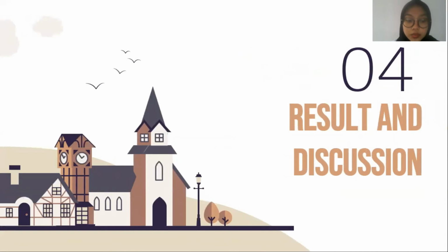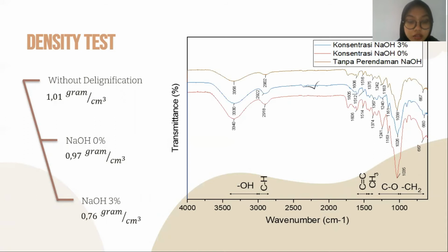And then the next chapter is about the result and discussion of this research. This is the result of the density test. Fiber density without delignification is 1.01 gram per cubic centimeter. And then fiber density with immersion without natrium hydroxide is 0.97 gram per cubic centimeter, and fiber density with 3% natrium hydroxide immersion is 0.76 gram per cubic centimeter.